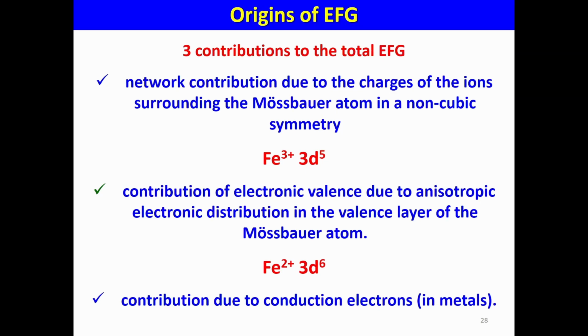Now, if you have a change of the symmetry in terms of crystallography, you might see some changes. And I hope to show you some examples which illustrate how sensitive the technique is. Okay? In the case of iron 2 plus, you will see some evolution versus temperature, or better said, at low temperature the splitting will increase, and you have to apply the crystal field theory.